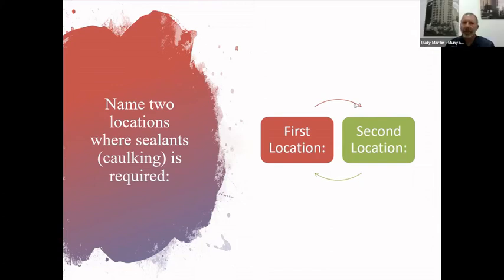So it looks like someone did a 10-year paint system with a 10-year sealant. That still needs to be inspected after 7 years. I think that's a good rule of thumb, and I think that was a smart move. If you have everything up there, your drops and your scaffolding, you do a 10-year system and then the 10-year sealant. And I agree, we see a lot of times that people put what we call a beauty bead, where the sealant is already in the window and they just put a bead over that and cover it up. Well, you're not going to guarantee proper adhesion. So complete removal and replacement is the way to go if you're flirting with that.